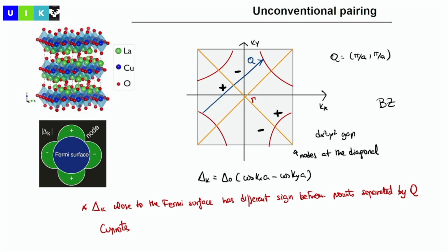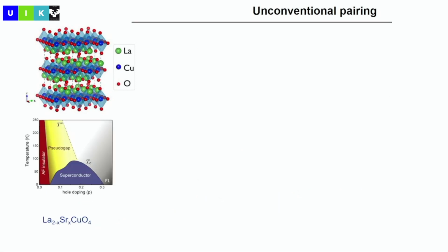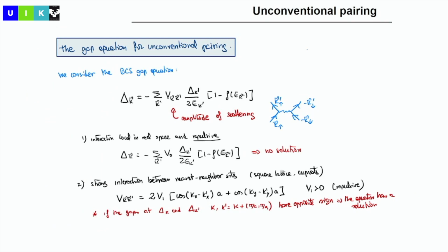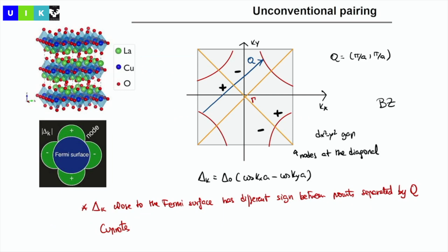What we saw is that for these states, with the interaction given by this term here, we can have a solution of the gap equation if the gap function changes sign going from one k point to the other, between k and k prime. If the function has to change sign, it needs to go to 0 somewhere in your Brillouin zone, because you want to go from positive to negative. This is what we call the nodes. So you can circumvent the electronic repulsion by having nodes in your order parameter.